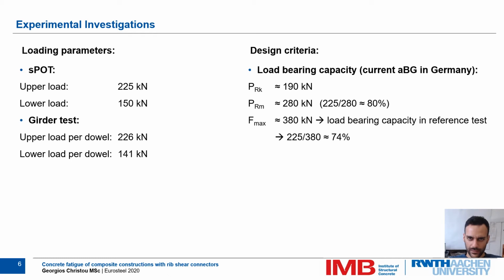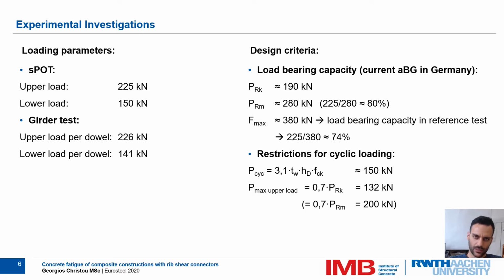Regarding cyclic loading, the current technical approval suggests a restriction of the upper load to approximately 70% of the characteristic load-bearing capacity, and a further restriction regarding multi-axial concrete damage, which is in our case approximately 150 kilonewtons. Since we were interested in fatigue failure, which shows particularly at high loads, a further increase of the upper load would lead to the steel girder reaching the yield strength and was thus not possible in this case.